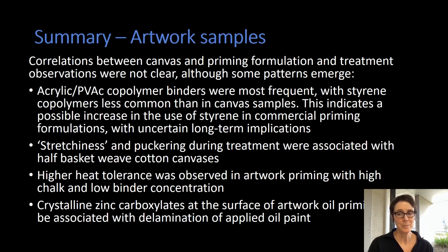One of the main recommendations from this research is for painters to avoid leaving commercial priming layers exposed as a white colour in their paintings. This is because styrenated copolymers left exposed as part of the painting image may be vulnerable to yellowing from UV radiation over time. Thus, it is recommended that priming should be covered with paint.